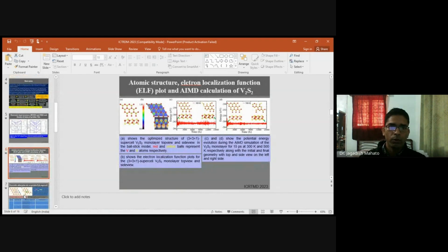Then A shows the geometry optimized 3x3x1 supercell of the V2S2 monolayer. Top view and side view are shown in figure A. B shows the electron localization function plot, and C and D show the AIMD calculation, where we plot the potential energy evolution during the AIMD simulation. AIMD means ab initio molecular dynamics simulation at 300 K and 500 K, which tells us that the structure is quite stable in this temperature range.